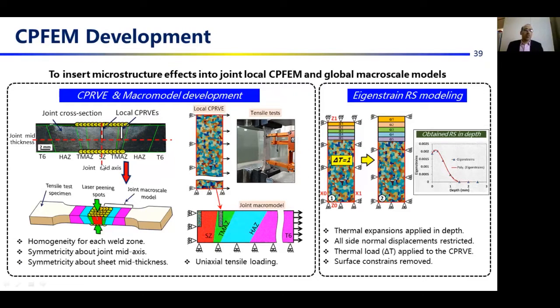For the CPFEM development, CPRVE models are developed based on the assumption of homogeneity of the mechanical properties at each zone and the symmetry about the joint mid-axis and the sheet mid-section. And the loading simulation is applied on both CPRVE and the joint macro-scale models to obtain the joint local and global tensile properties. And the eigenstrain method is utilized to simulate the laser peening-induced residual stress.